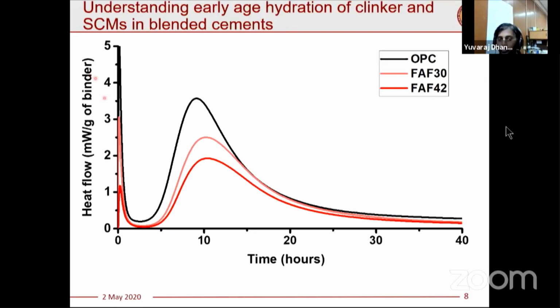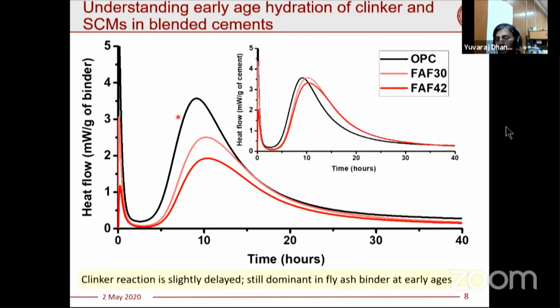So we know the amount of cement which is present in the binder, and when we produce a normalized curve where the heat flow is normalized to the gram of cement present in the binder, this is how it looks. So we can see, irrespective of fly ash, the heat flow per gram of cement is nearly similar, which confirms that a major portion of the cement is what is reacting. However, what we also notice is there is a slight shift in the peak to the right, which means the reactions happen at a slightly slower pace. However, the major amount of fly ash remains inert during this period. So do all the SCMs react at the early ages?